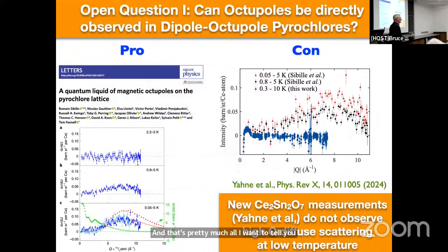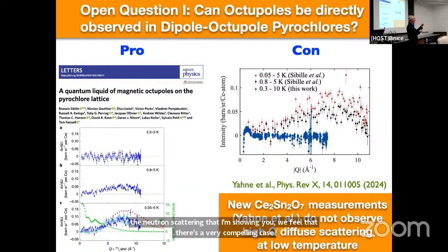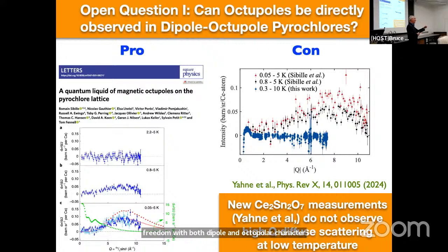I'll just finish with these 2 open questions. We're looking at quantum spin ices in dipole-octupole pyrochlores. Okay, so the open questions focus on 2 points. One point is, can we observe the octupoles directly? Actually, all the neutron scattering that I'm showing you, we feel that there's a very compelling case that there are spin-1/2 degrees of freedom with both dipole and octupolar character, but the neutrons are primarily sensitive to the dipolar character. So the question is, can we observe the octupoles independently of the dipoles? And can we follow what the octupoles are doing independently of the dipoles? So that's an open question.